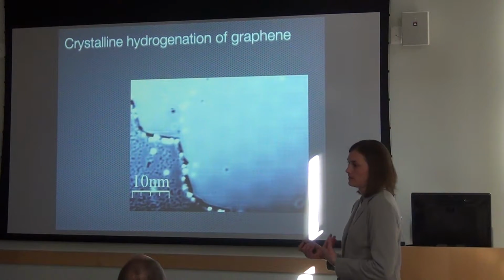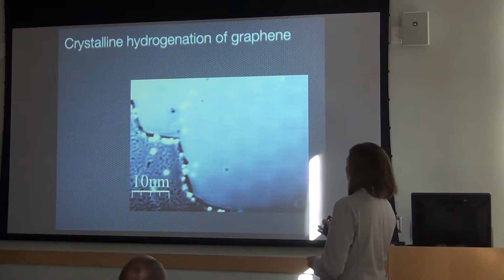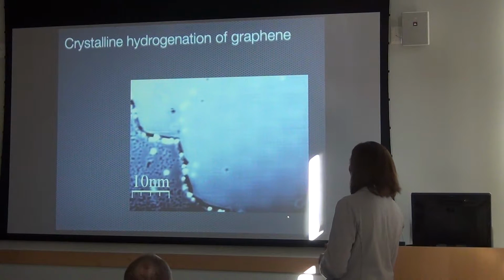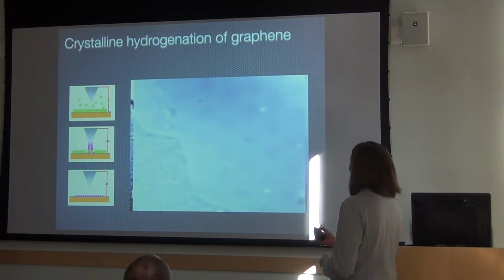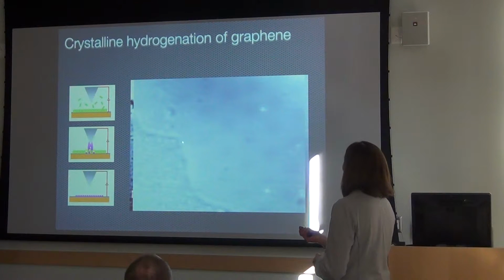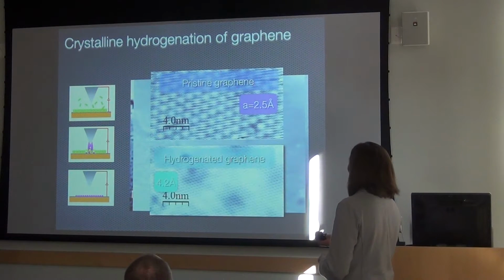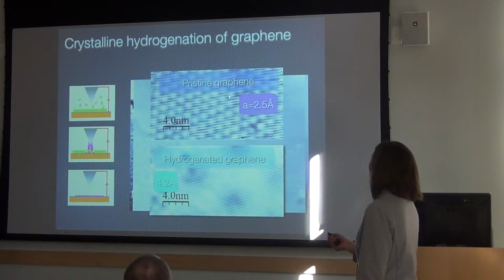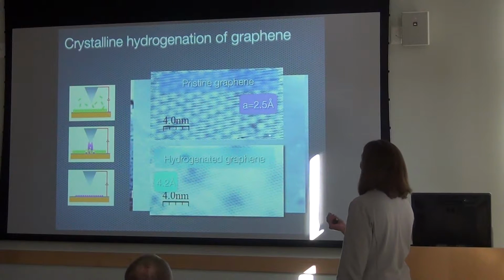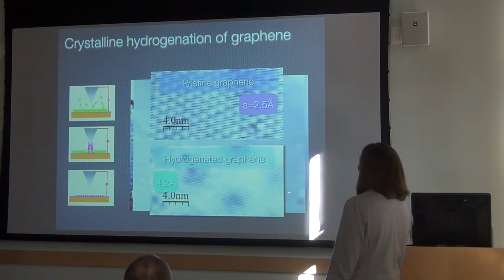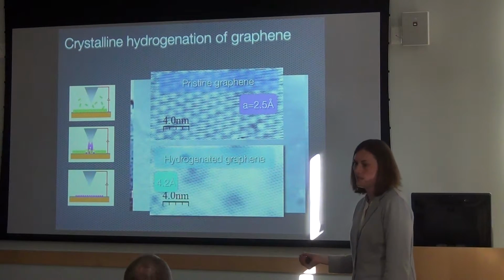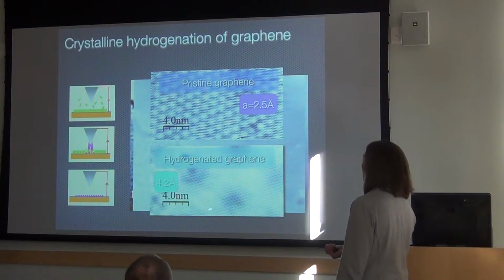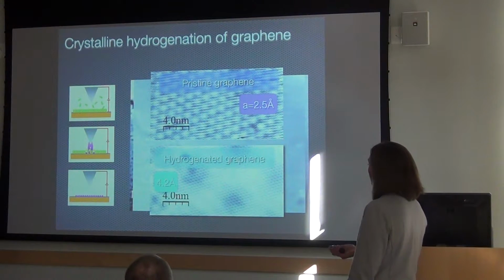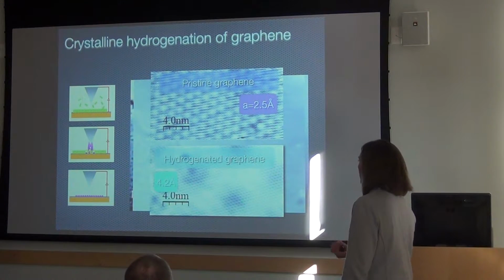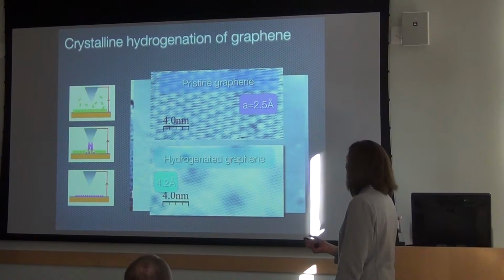We did this a number of times, and this is the most common result that we got that I'm about to show here. This is a clean graphene area, and this is the copper over here. After all of these steps, we ended up with this, which you can't see very well, but I'm going to zoom in in a second, where there's a pattern over the entire area. This is a comparison between the pristine graphene lattice with a particular moire pattern, where the lattice constant is 2.5 angstroms, and this hydrogenated graphene lattice that we most commonly get, which has a triangular structure as well, but the lattice constant is 4.2. We're still trying to understand what these hydrogenated lattices actually are, where the hydrogen is.